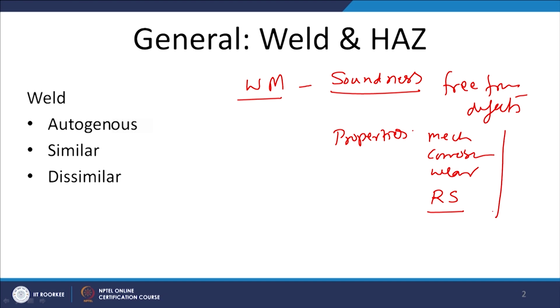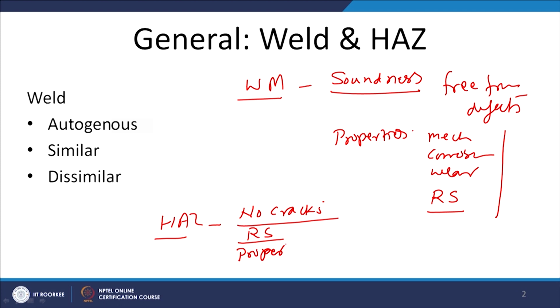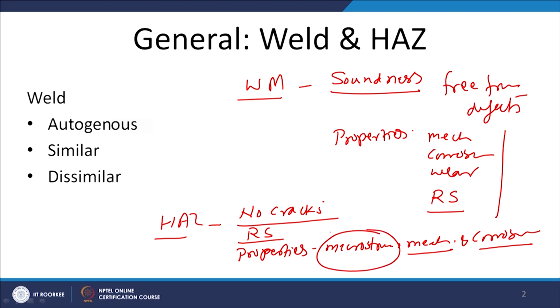or poor. Apart from this, the heat affected zone properties are also looked into. We see whether the heat affected zone is sound, meaning no cracks, and the kind of residual stresses present, and the kind of properties it has in terms of microstructure, mechanical properties and corrosion properties. Sometimes hardening takes place, which leads to embrittlement; sometimes softening takes place in the heat affected zone, which promotes fracture. Unfavorable metallurgical transformation in the heat affected zone lowers the corrosion resistance, and all these things happen due to unfavorable metallurgical transformations, meaning the development of microstructure.